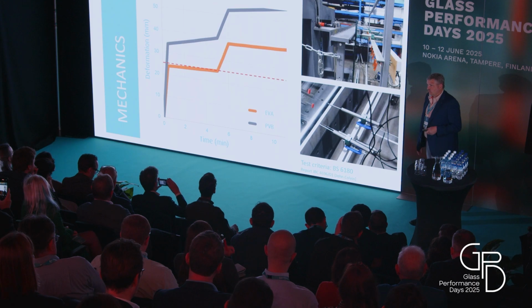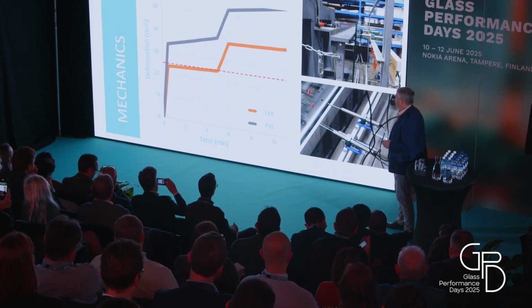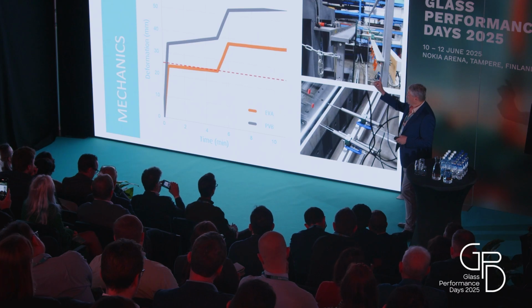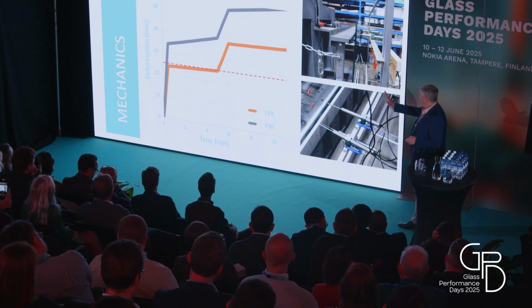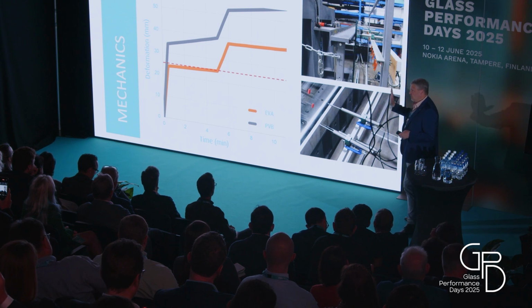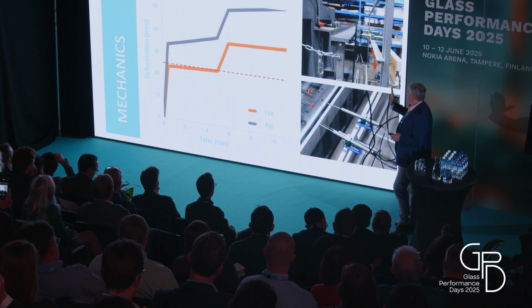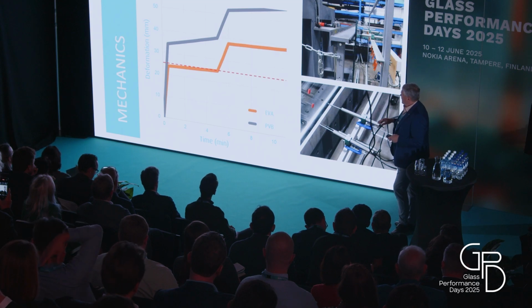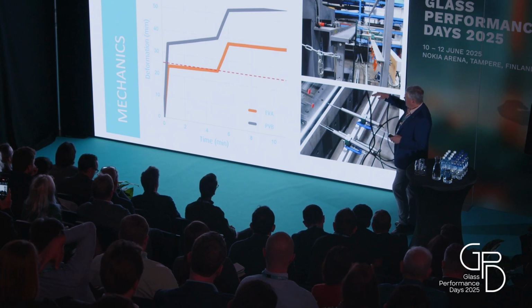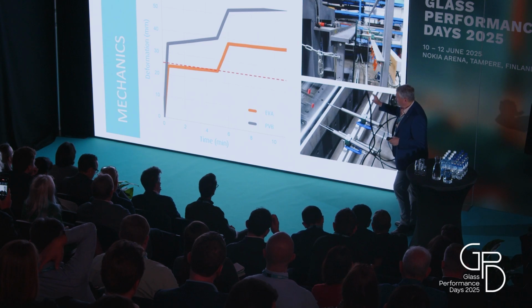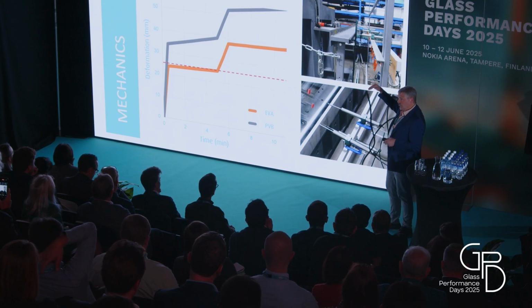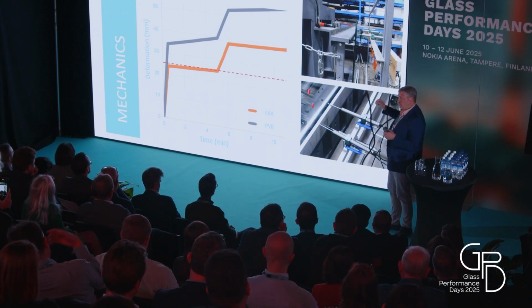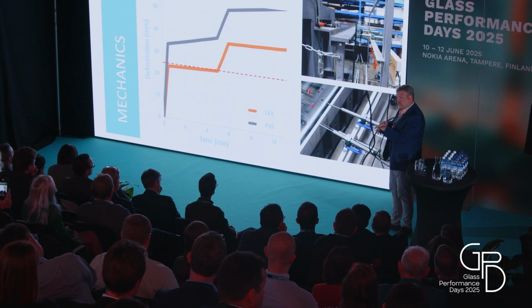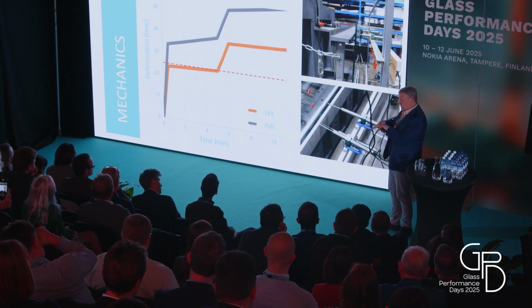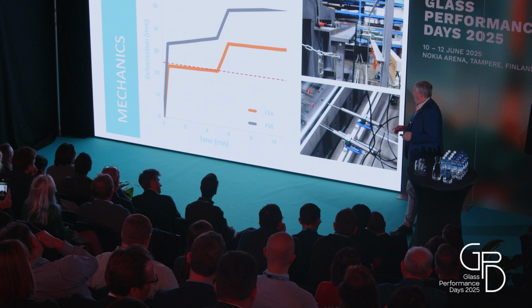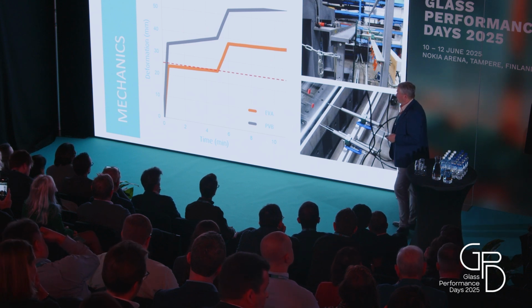The test here was a comparison between EVA cross-linked and PVB, and you see the difference. The dark line is PVB. Of course, this was, I think, 8 millimeter toughened glass and 0.76 interlayer. There is certain deflection, but the difference is not only the deflection value. The difference is that you have a so-called creep effect for PVB, and this is because the thermoplastic chains are moving between the glasses. It means there's a certain moving effect, and this is what the cross-linkable film will not do once cross-linked.